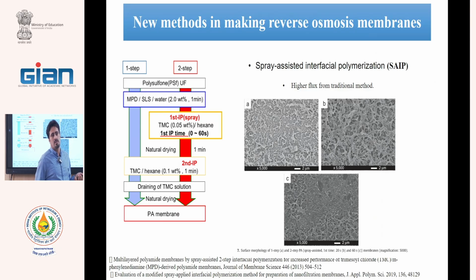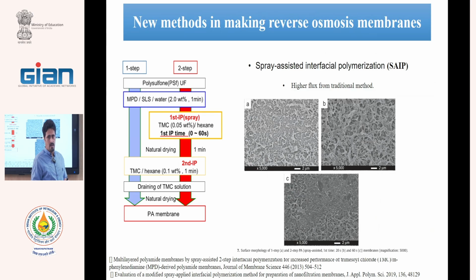In the traditional method, we immerse the supports in a monomer bath. In this case, we need a large MPD volume for filling the bath. We need, for example, 100 milliliters, but we must fill the bath with 2 liters for good dispersion of the support. Therefore, one of the reasons for using spray-assisted interfacial polymerization is reducing the chemical consumption.